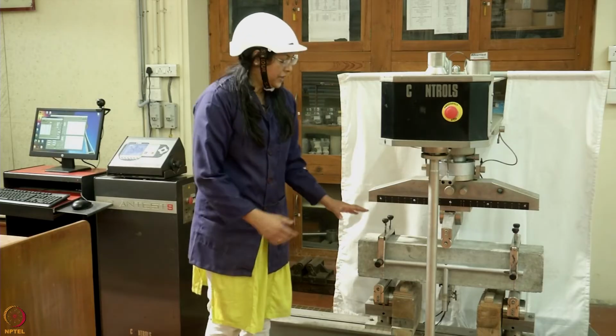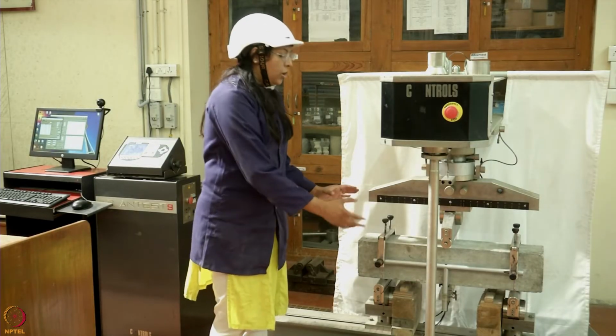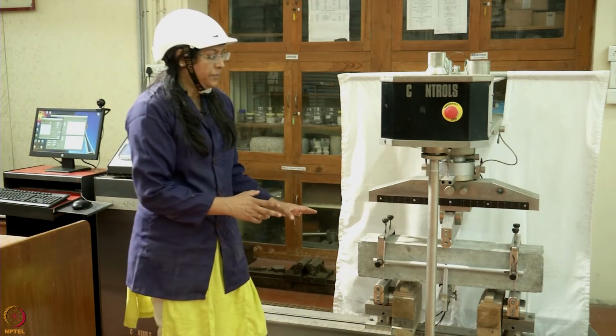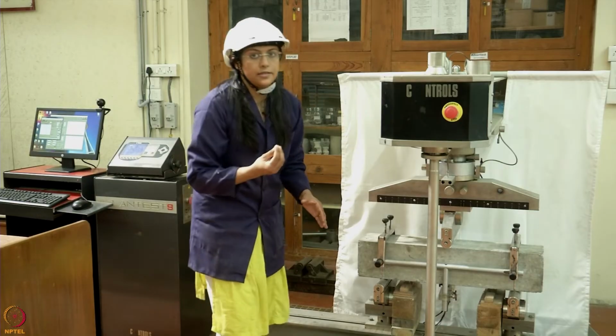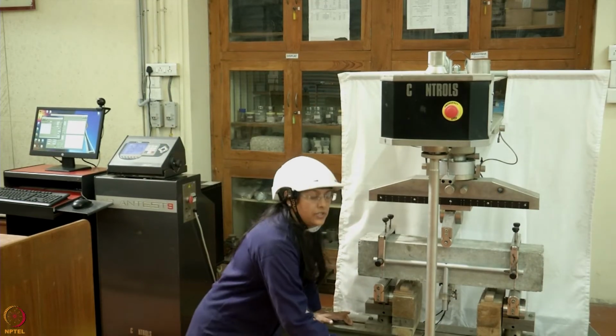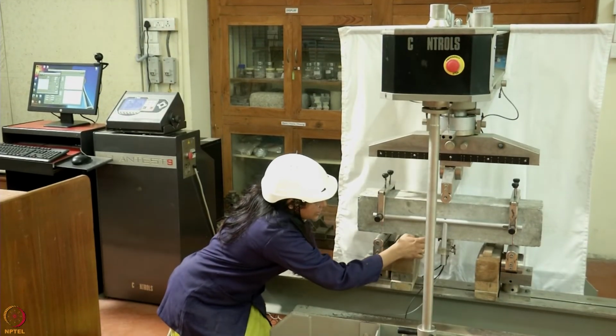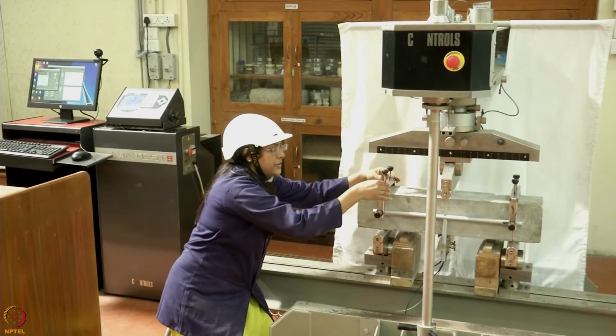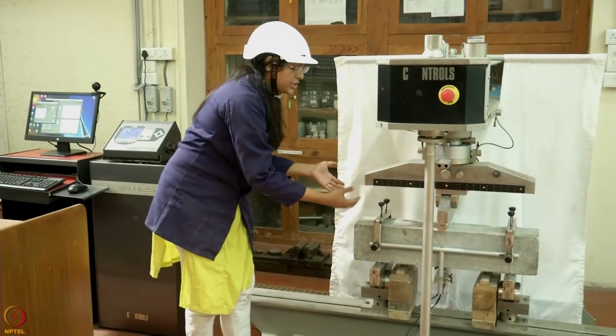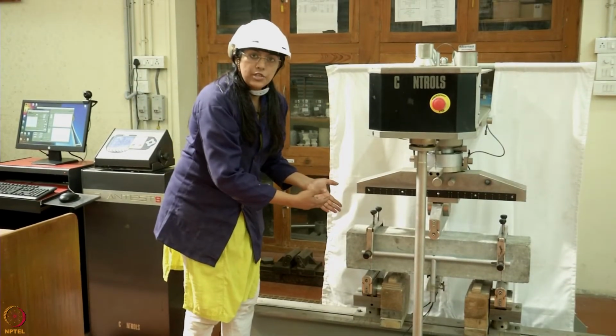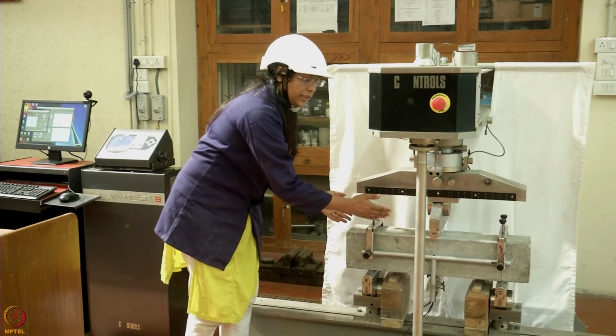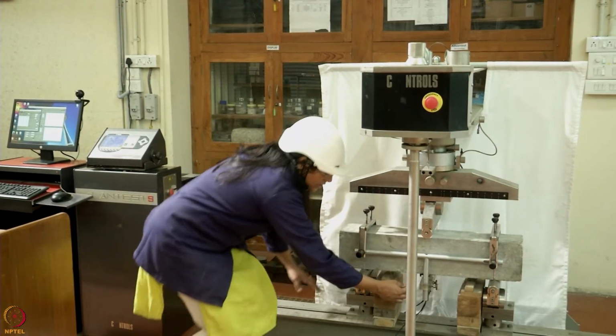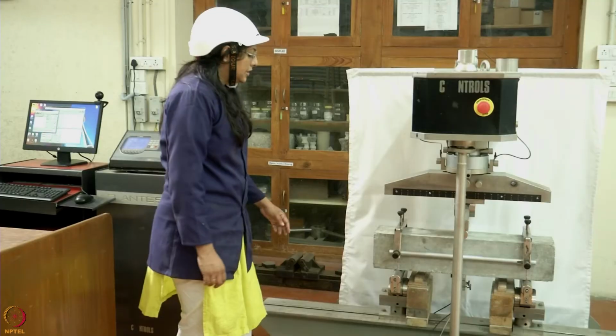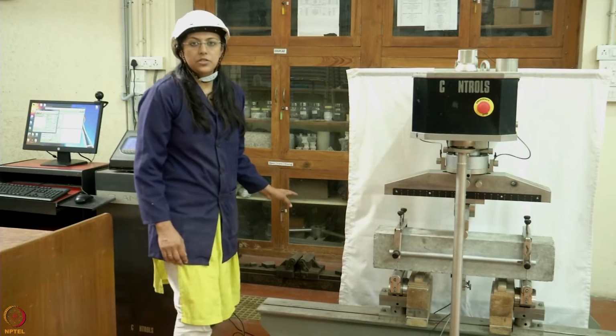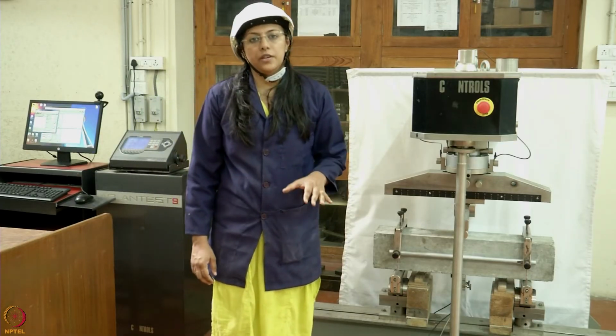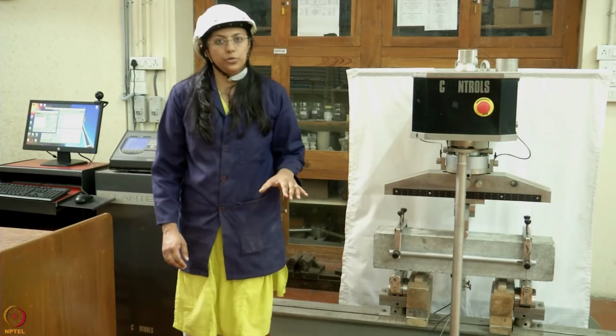This is the setup in which we have mounted our fiber reinforced concrete specimen onto the testing system. This is a closed loop testing system, and we have mounted three sensors, as I've explained before. That is the clip gauge with which we control the test, here, and LVDTs, which are fixed on either side of the specimen onto the rigid frame, which is fixed to the specimen by means of a C-shaped collar. The deflection of the specimen we consider by taking an average of the readings of the two LVDTs on either side. But the control is done with the clip gauge CMOD, which is mounted onto the knife edge at the midspan. These sensors are connected to the data acquisition system, through which we acquire data through our interface. Now let's see how we do the testing.